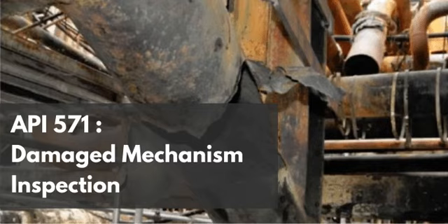Right. You take a powerful medicine, the ferrite, to cure one fatal disease during fabrication, which is the hot cracking. But the side effect of that medicine is that you permanently introduce the ferrite phase into your system, leaving you entirely vulnerable to a long-term chronic disease. 885 embrittlement. That is exactly the reality.